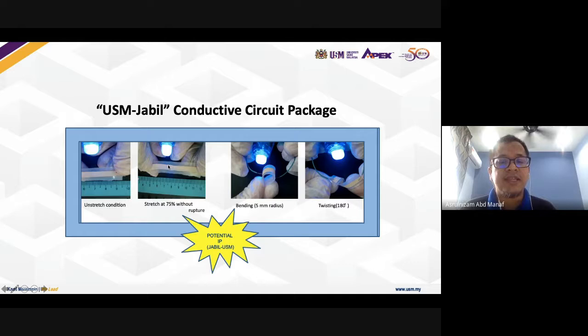This was at that time, 2017. They used PDMS, so the ink is a mixing between the PDMS and the silver flake. So that means it is good in terms of conductivity, since with flake the intensity is also the same. That means it's a good conductor.